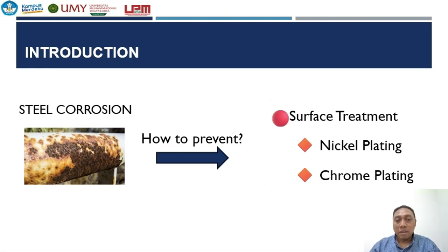The surface treatment method involves applying a metallic covering of nickel and then chrome to a metal object. The nickel layer is applied to enhance adhesion strength and establish a uniform surface, while chrome plating enhances corrosion resistance and achieves a desirable aesthetic appearance.